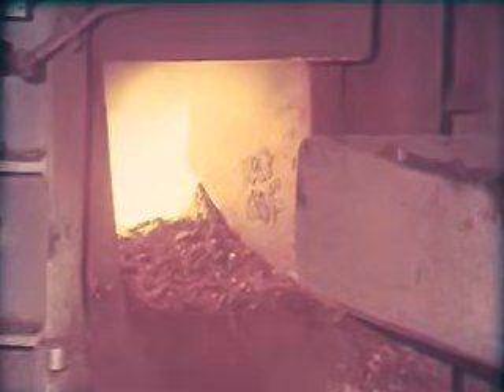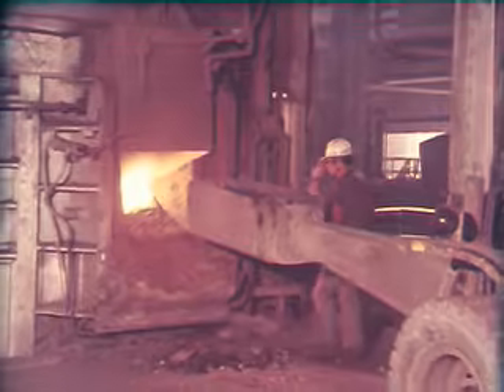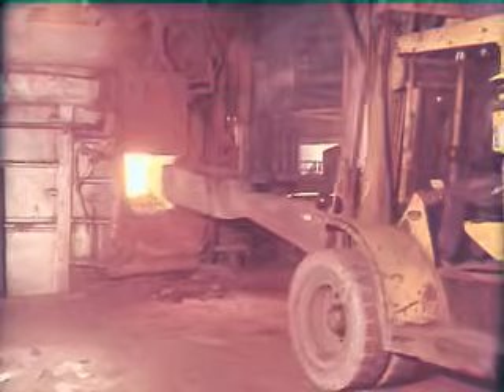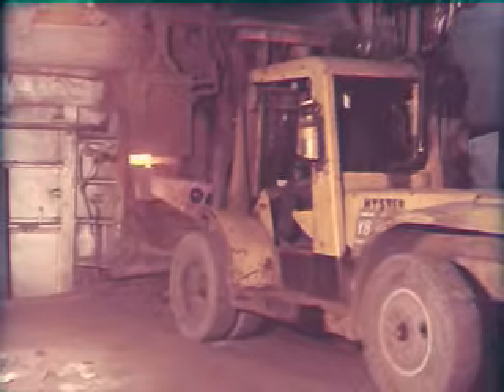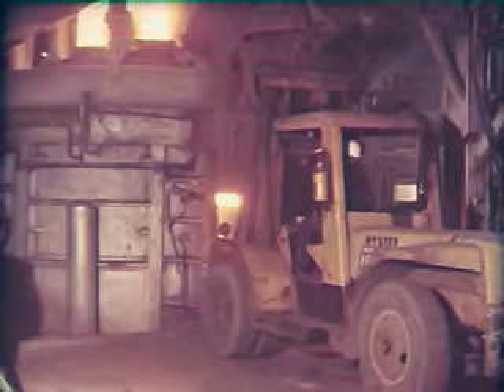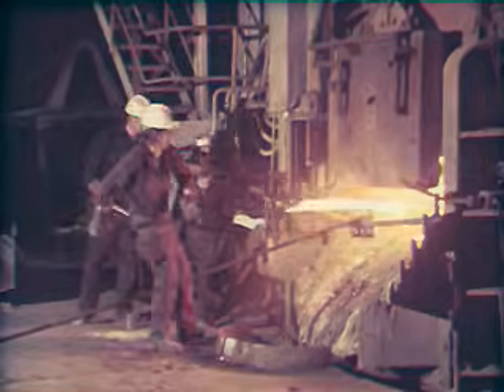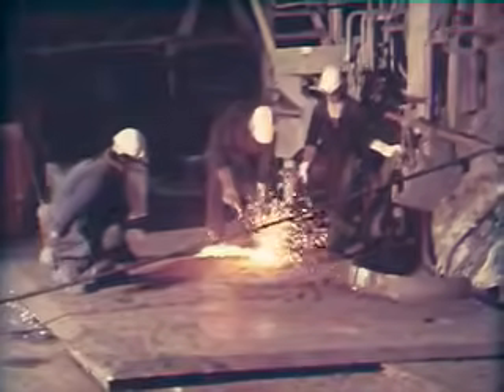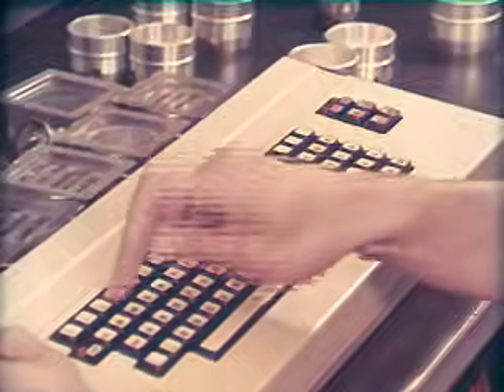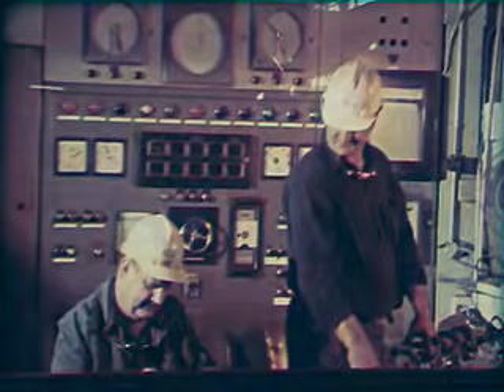Various elements are then added depending on the grade of steel being made. Special steels are highly complex formulations and can contain nickel, chromium, molybdenum, vanadium and tungsten, as well as other components. During the melt, frequent samples are taken from the furnace and sent direct to the Comsteel laboratory. Here the sample is immediately analysed in a direct reading emission spectrometer or X-ray spectrometer. The analysis is teleprinted to the steelmaker at the furnace so that he can make any necessary additions to the steel to match the required specification.